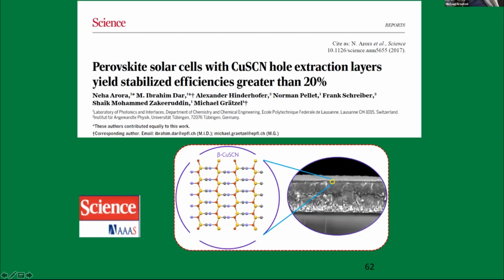And so we had submitted this paper to Science, where we changed the hole extraction layer. We didn't use the organic arylamine anymore, but copper thiocyanate. And then the editor was interested in the paper, sent it for refereeing, and then one of the referees came back and said, well, they haven't shown the operational stability. I'm sure they have done the test, so ask them to put the data in. And we had done the tests, and we put the data in. It showed a 20% decline in 1,000 hours, as I said, at 60 degrees, full light on it and maximum power point tracking. And so we thought 20% wasn't bad, but the referee didn't like it, and the editor rejected our paper and said, don't come back even if you solve that problem.